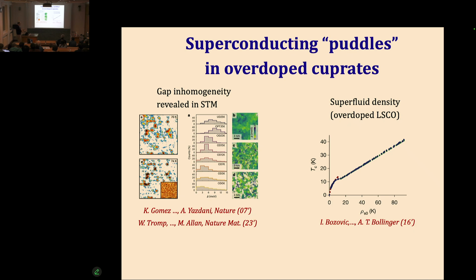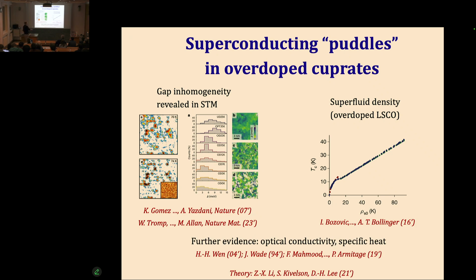There's evidence from the behavior of the superfluid density as a function of doping. It looks like there's a big fraction of the electrons on the overdoped side that are not participating in the superconductivity, that are not condensed. And there's further evidence in optical conductivity and specific heat and so on. There's a nice theory of that by D.-H. Lee and Steve Kivelson. The idea is that in an unconventional, non-S-wave superconductor, in the presence of disorder, superconductivity would ultimately be destroyed by disorder, but not uniformly. There would be some regions where it would be destroyed much before other regions, and that's the origin of these superconducting puddles.